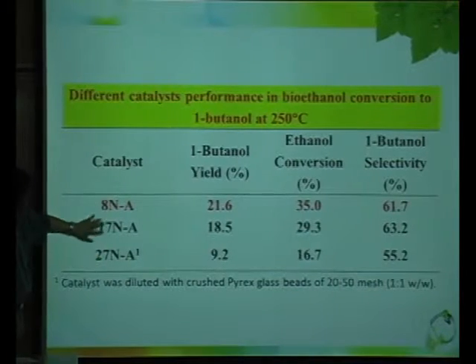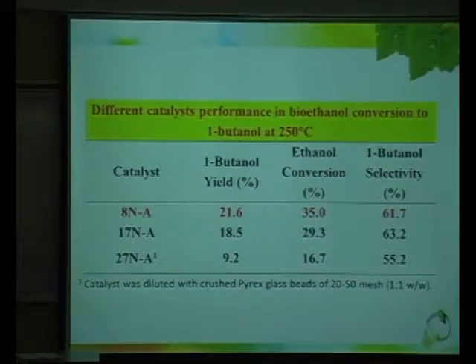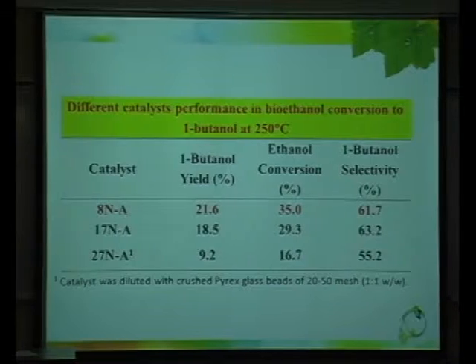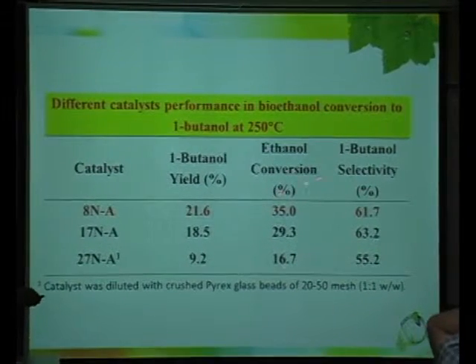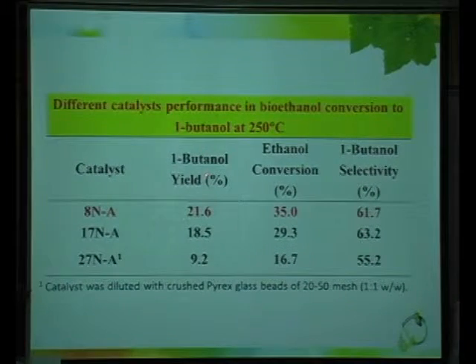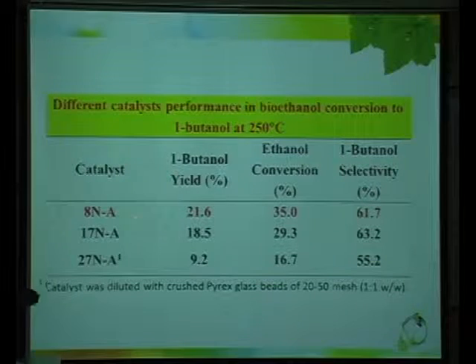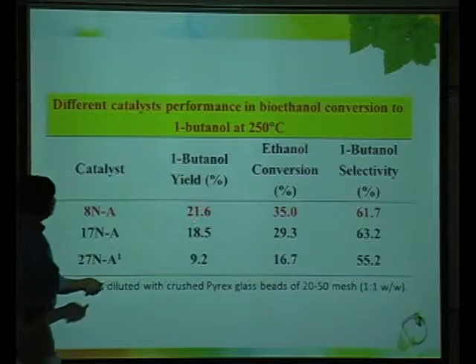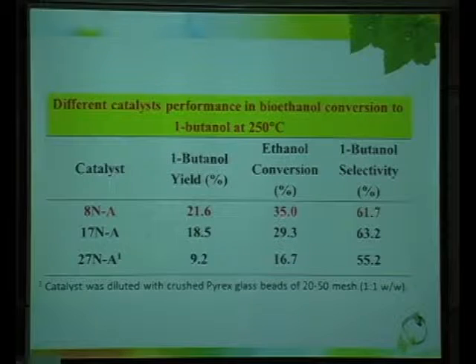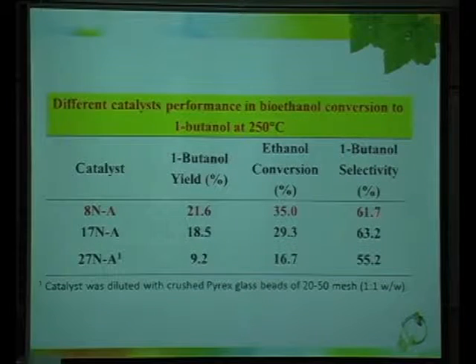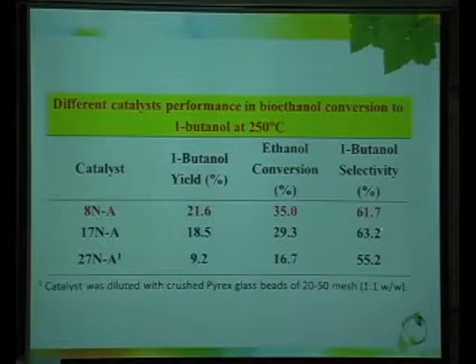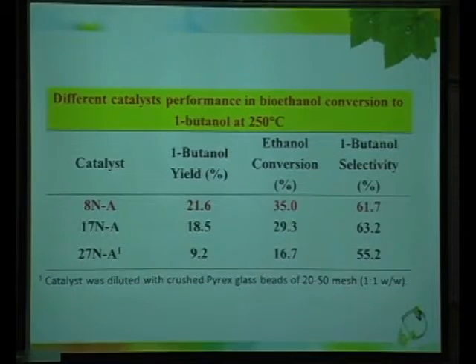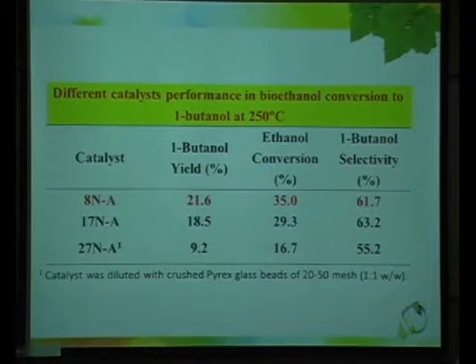We have three types of catalysts tested here. This is the butanol yield, this is the conversion, and this is the selectivity. The best catalyst gets more than 20% yield, with 35% conversion and selectivity at 62. The second catalyst has even slightly better selectivity, 63, but the conversion is a little bit low, and the yield is low.